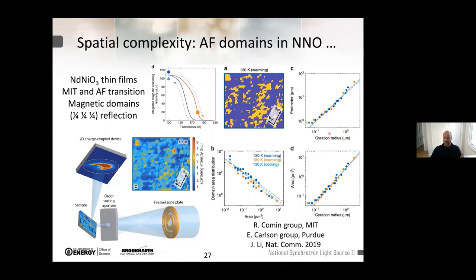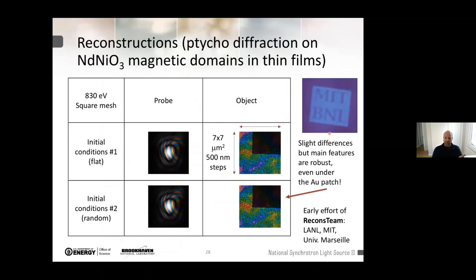And so you can get really quite an interesting insight, over orders of magnitude, into the distribution of the magnetic domains or a subfamily of your magnetic domains in your sample. So we can also reconstruct, obviously, and the same or similar kind of information can come from the direct reconstruction using the Fourier inversion.